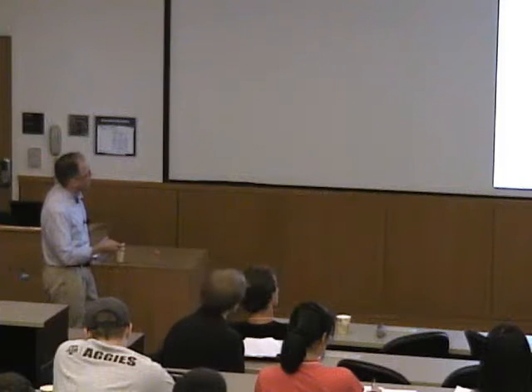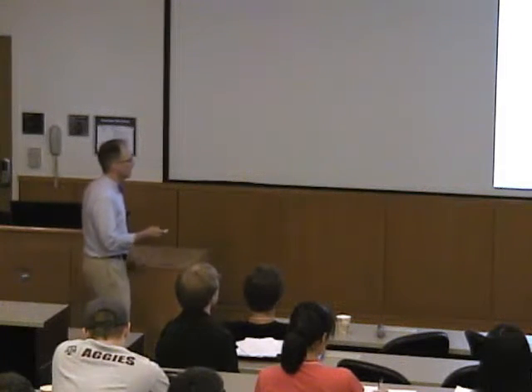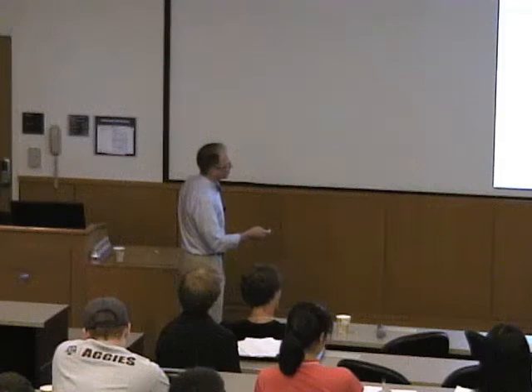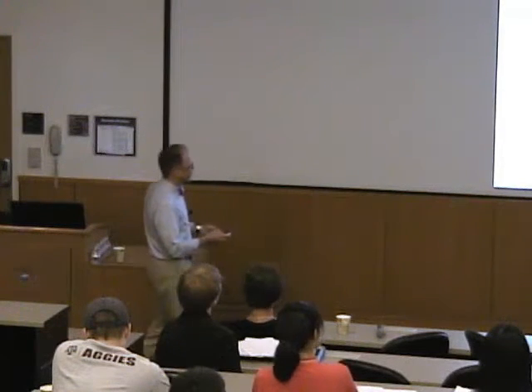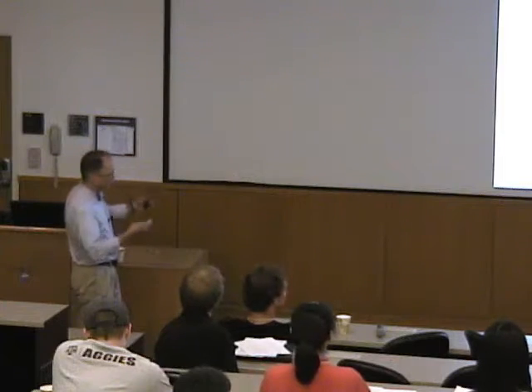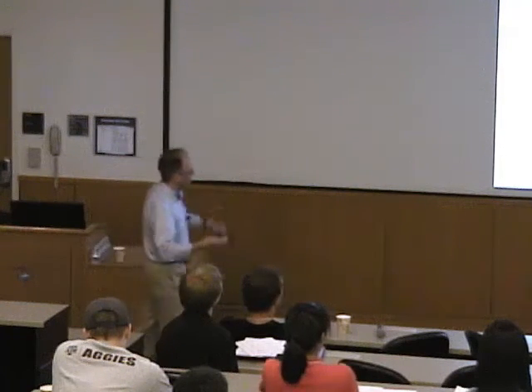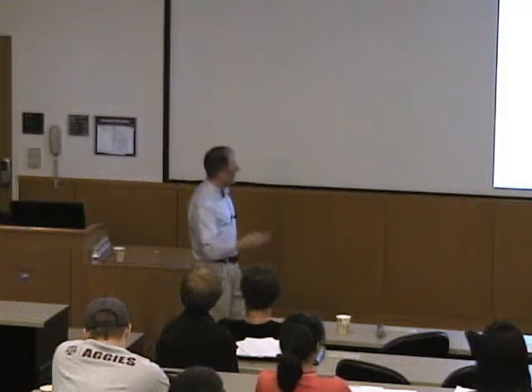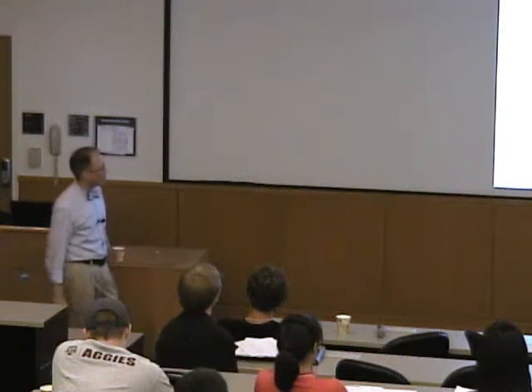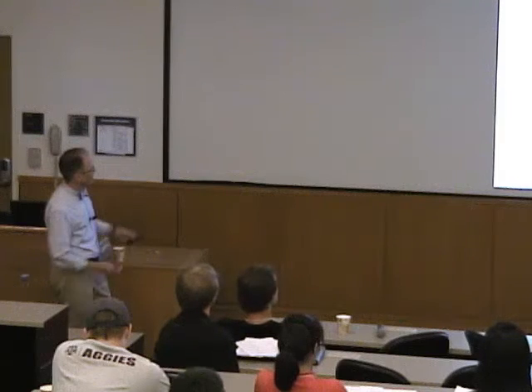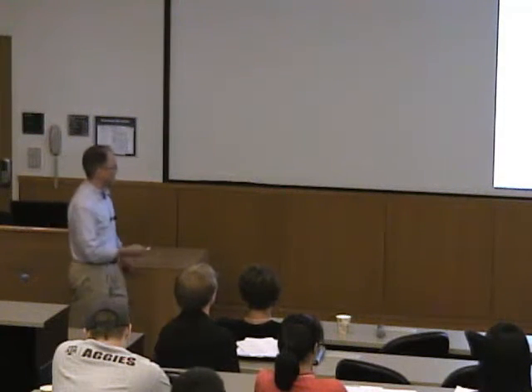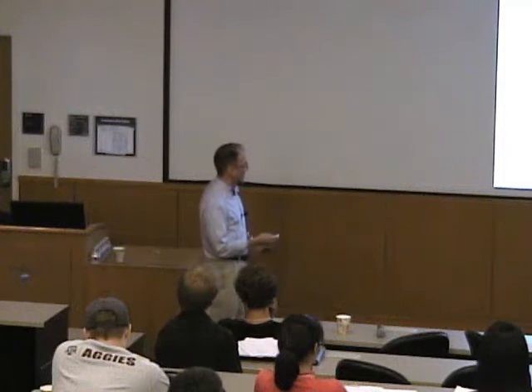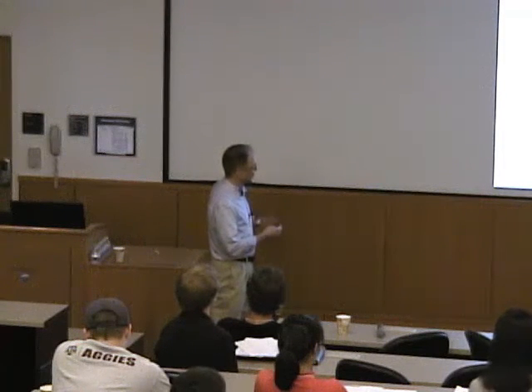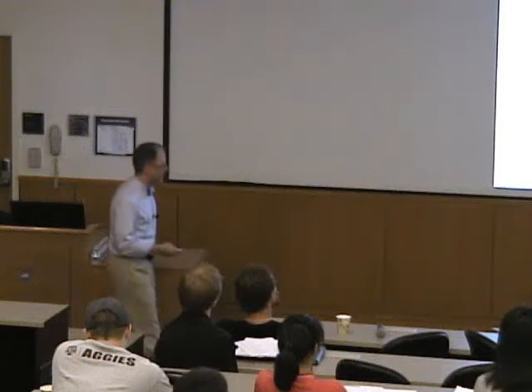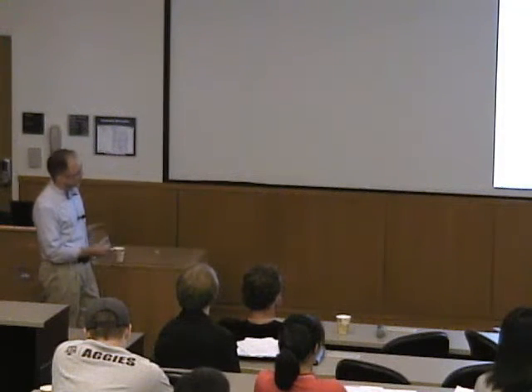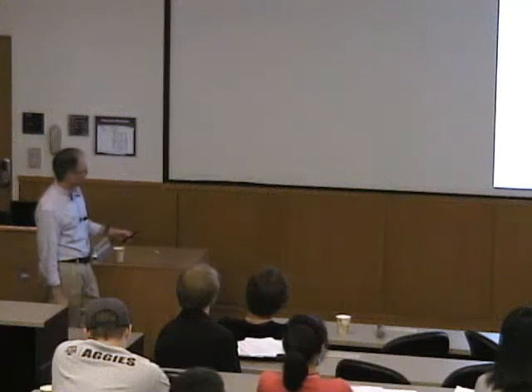where again we have a similar relationship between an electronic coupling factor with now what we refer to as an interfacial electron transfer rate, the rate by which the electronic coupling can occur. And it doesn't have to do with the internal wiring of a complex metalloprotein, let's say, but literally it just has to do with how well that metalloprotein or catalyst or whatever our molecule is going to interact with a given electrode, that we might be able to control or we may not be able to control. And under that Butler-Volmer regime, we would say that there's actually not going to be a dependence upon the reorganization energy as long as we're not at an extreme overpotential.